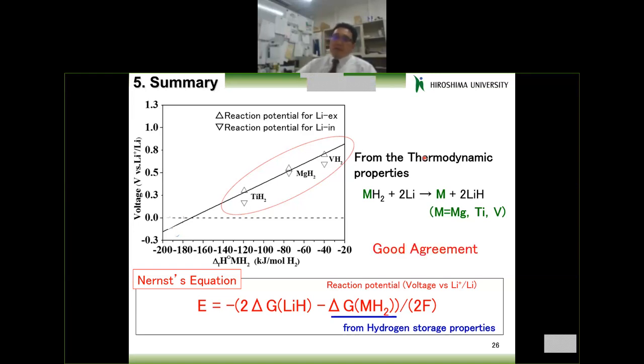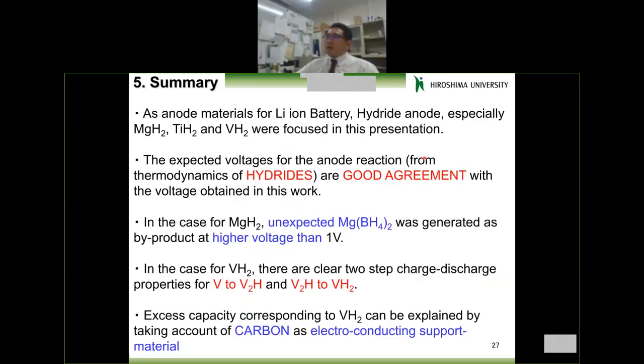Okay, quite good agreement was observed. And that is summarized. Actually, we focus on quite typical hydrogen storage materials for the anode of lithium-ion batteries, and some good agreement was confirmed. And of course, each result shows some strange properties. For the case of magnesium, unexpected magnesium borohydride was generated.